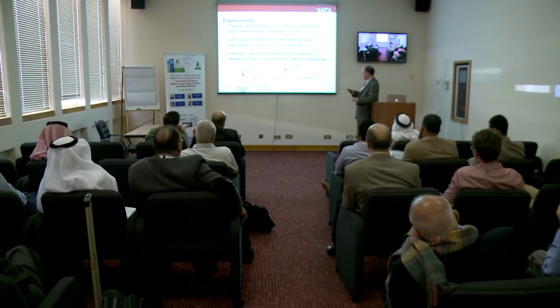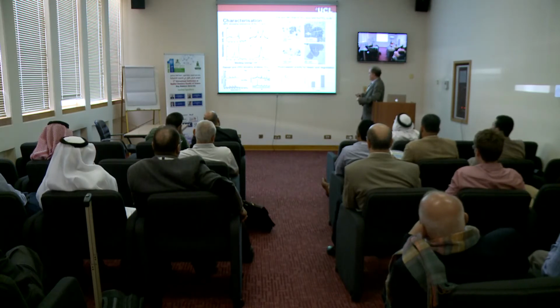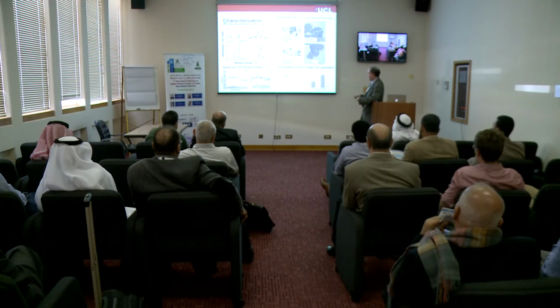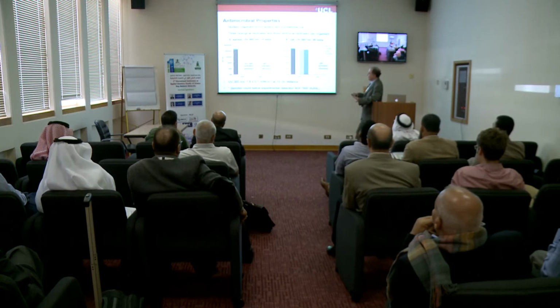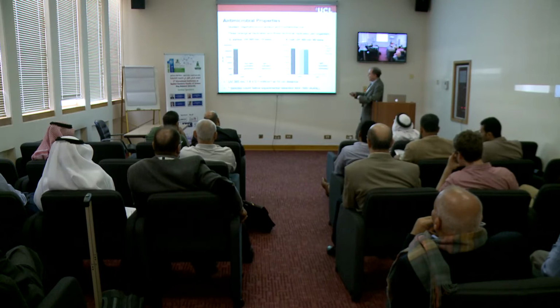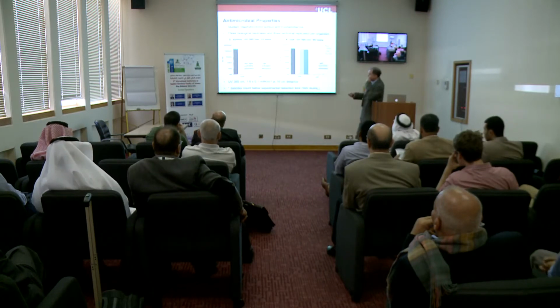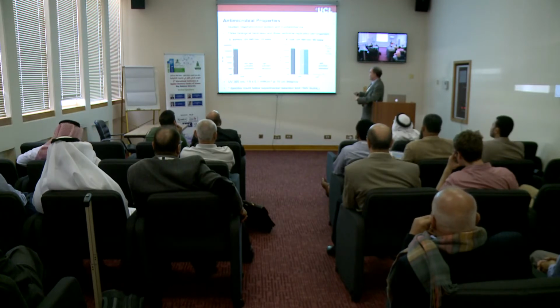So what we try to do is to come up with surfaces which will kill bacteria. So relating to the work we've done with titanium dioxide particles, we combine that together with oleic acid to make these gold cap nanoparticles. And when we've incorporated those gold cap nanoparticles, we showed that they act as a photocatalyst and also they can be used to kill bacteria. Now this is using UV light irradiation, but we've also got systems which work with visible light, and this is the kills against Staphylococcus aureus. So basically this is our control numbers here, but when we add the light we kill it. The very surprising thing for these coatings is that they work in the dark as well, so they give us some kill without necessarily having light activation, and that shows what it's like against the gram-negative.